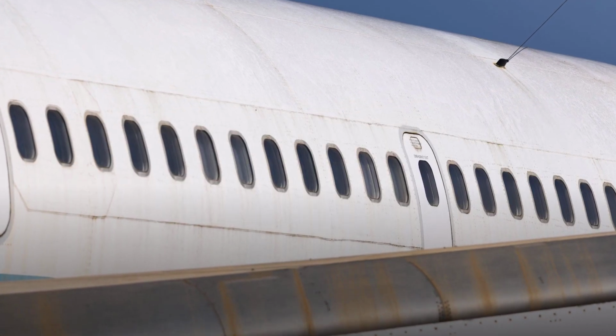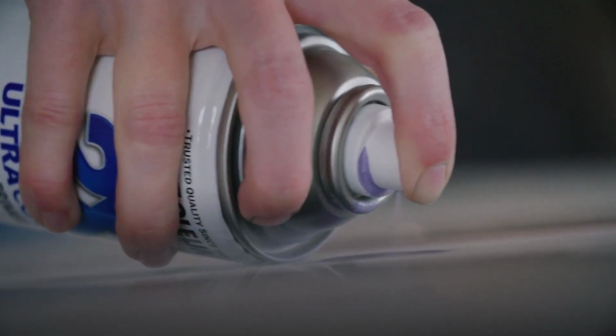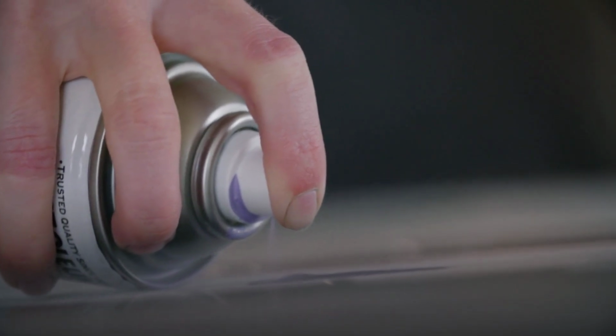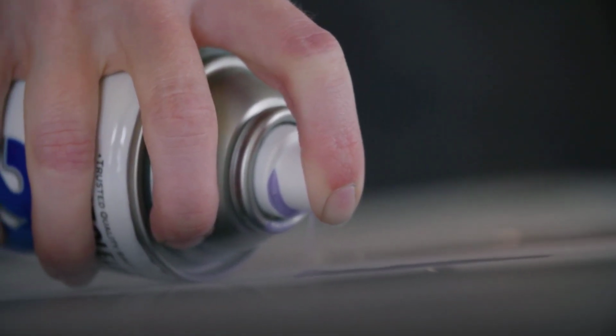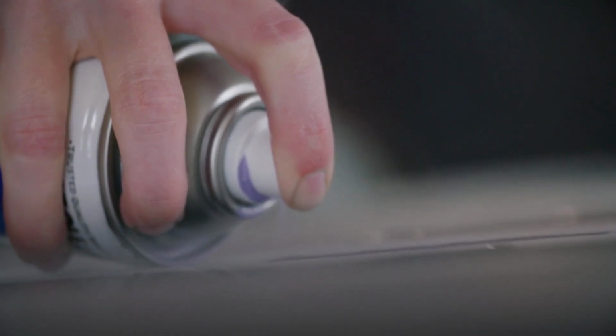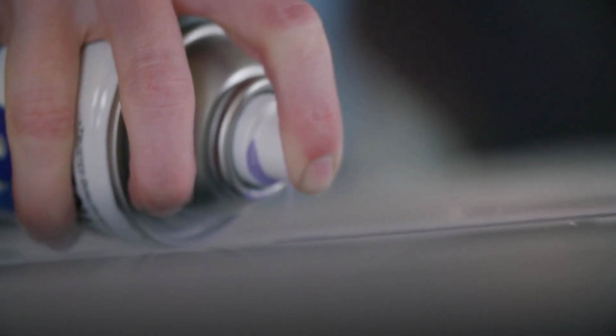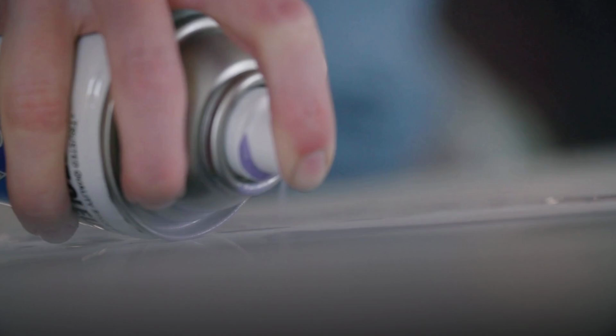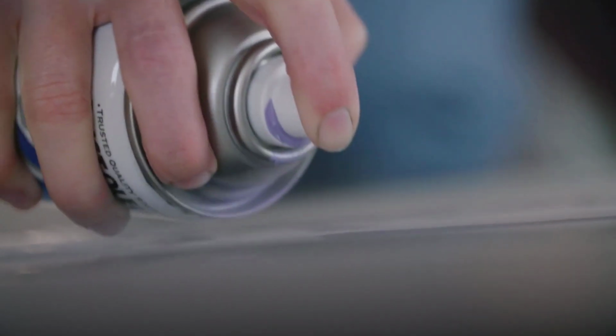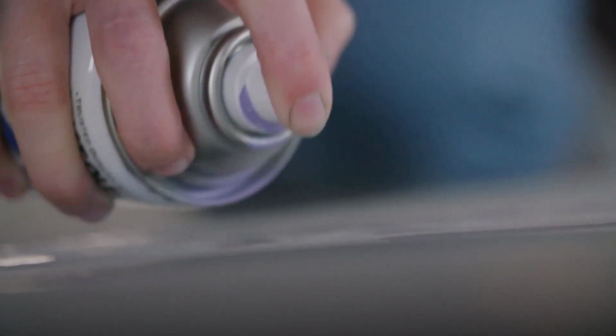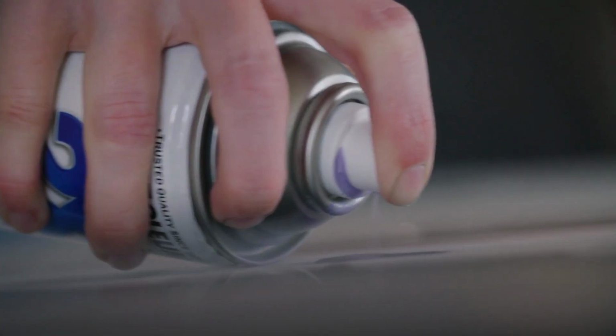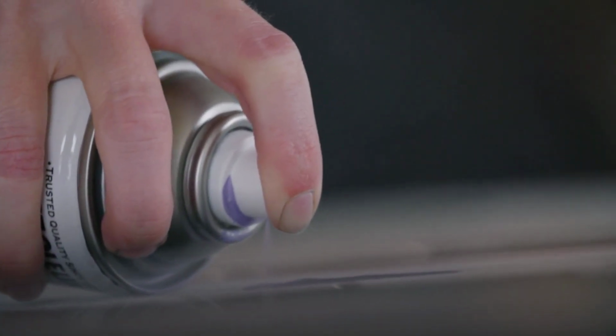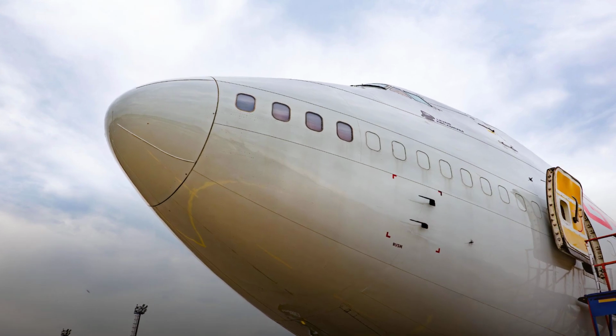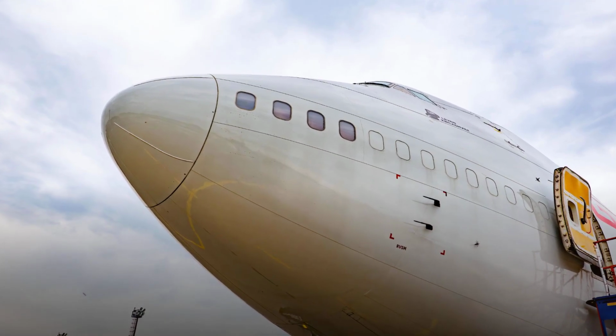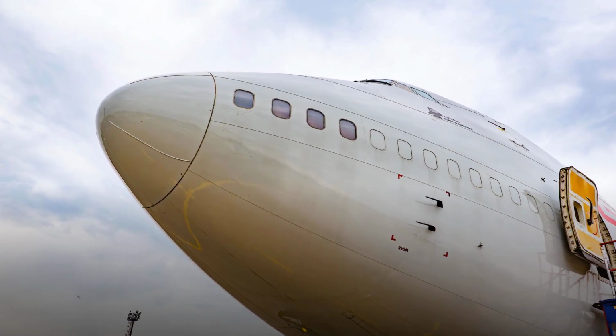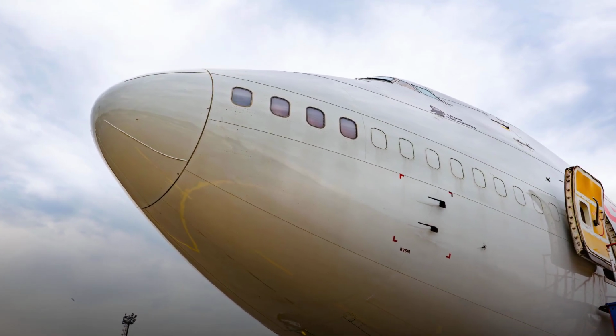The lap joints were sealed with an adhesive to ensure airtight integrity and prevent moisture ingress. This sealant, while serving its intended purpose, inadvertently concealed the burgeoning cracks from visual inspection. The NTSB investigation would later conclude that the existing visual inspection program was inadequate for detecting such hidden damage. The cracks were too small to be seen with the naked eye and were obscured by the very material meant to protect the joints, creating a deadly illusion of safety.